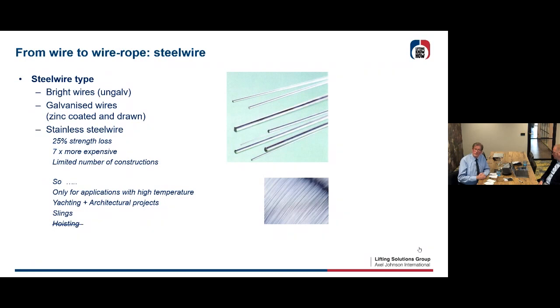There's another kind of rope wire, and this is stainless steel wire, inox. Well, we're not going to talk about stainless steel wire ropes this morning, because you have about 25% strength loss compared to galvanized or bright wires. It is 7 times more expensive, so take care of prices. And there are limited numbers of constructions in stainless steel wire ropes. So I would advise it only for applications where there are very high temperatures. If you use galvanized wires and bright wires, you can go up to 200, 250 degrees. Everything above that, you could use a stainless steel wire. They can go up to temperatures of about 500, 600 degrees in special stainless steel wire applications.